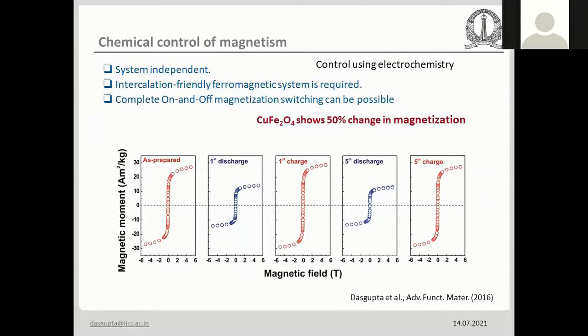Next, what we did, I did not go too much into detail because I don't have time. There was certain reason to believe that if we go from iron ferrite to copper ferrite, and then to zinc ferrite, we can have larger and larger control over magnetization, and that's what we did a couple of years later. And there we observed a 50% change in magnetization for copper ferrite. So the red hysteresis is as prepared. After first discharge, you can see that 50% reduction in magnetization.